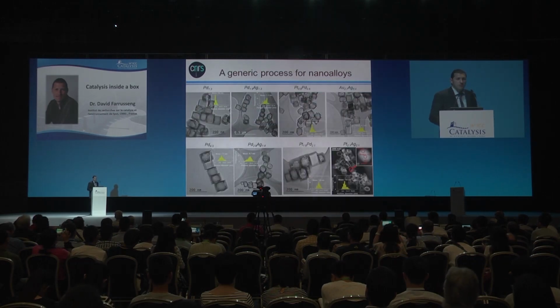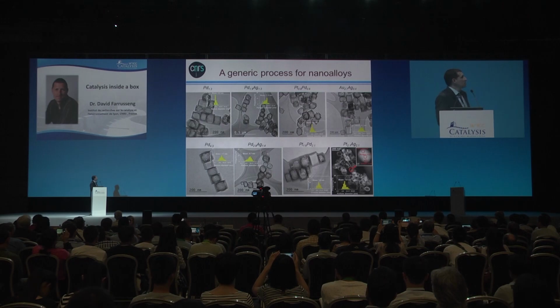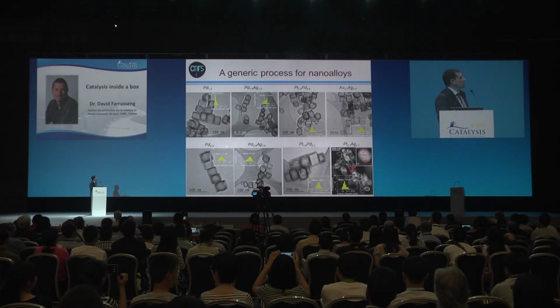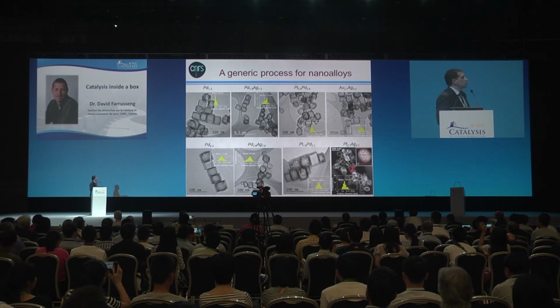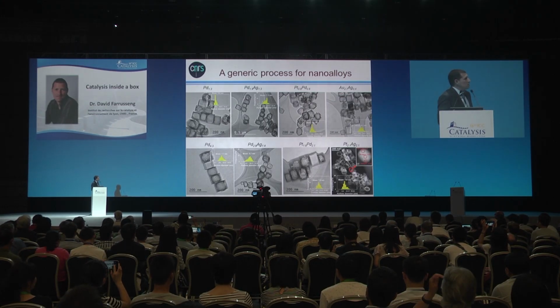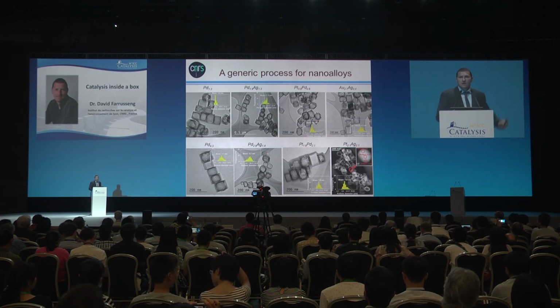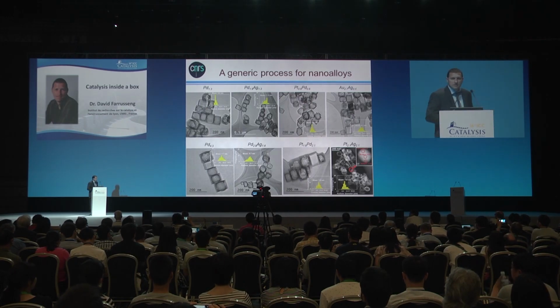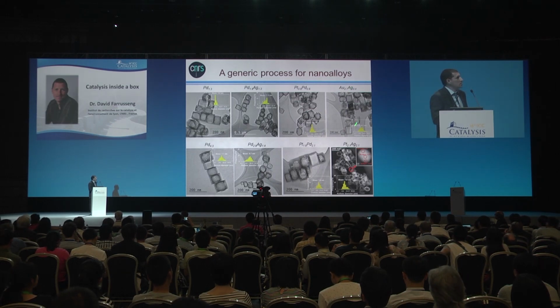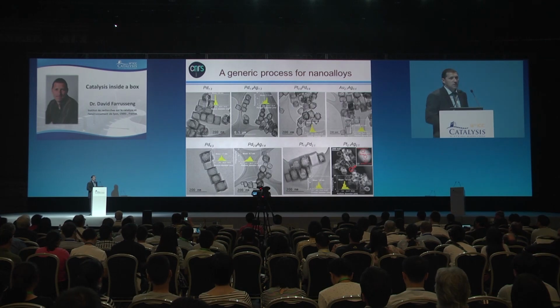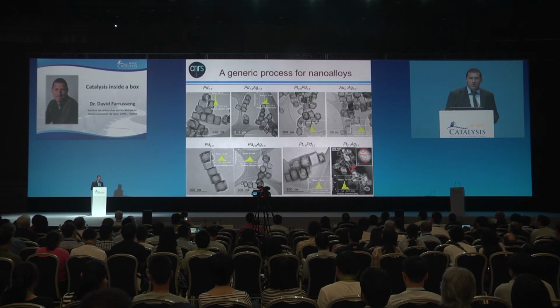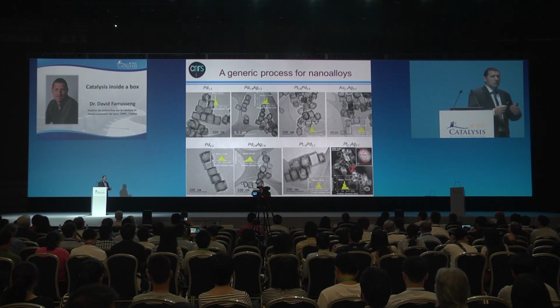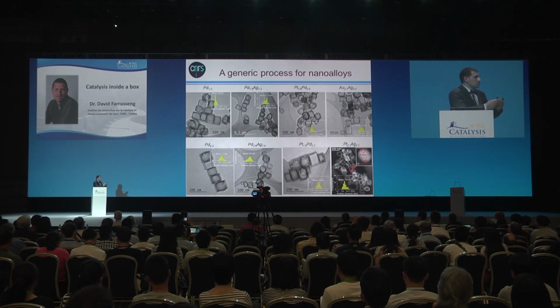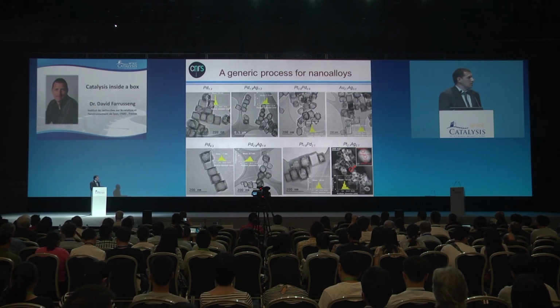And we repeated that for a number of alloys and sizes. You can see that for each case, we have a very narrow distribution of the particles. For example, in this example, we target 8 nanometers as the target size for the particles. But we have here 3 different alloys: gold-silver, platinum-silver, platinum-palladium. So in other words, it is really possible, and this method allows us to control independently the composition of the bimetallic particles and the size.